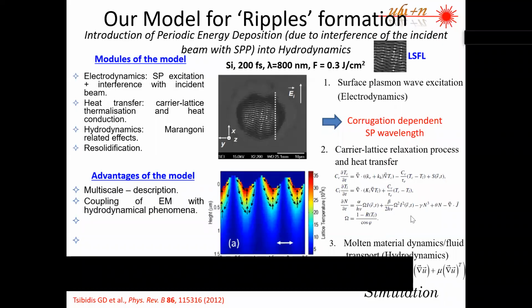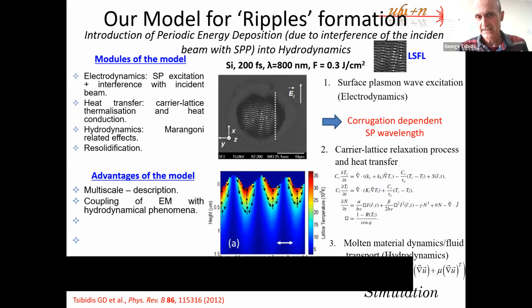Okay, so if I understood correctly, this depends on the material, right? I mean the periodic structure that you will get. If you shoot the same laser beam to another material, you maybe get a different structure. You need to have defects. You need to have corrugation on the surface. So it's not material dependent. It is surface dependent in principle. It is also material dependent, because the orientation of these waves depends on the dielectric parameters of the material. Dielectric materials and metallic materials dictate the propagation of these surface waves in different directions.